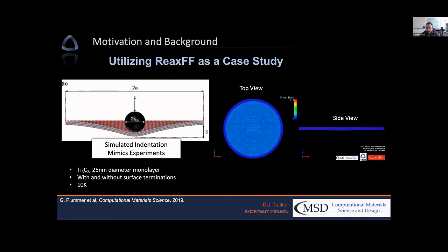We simulated the nanoindentation process as shown here on the right, up until the point of fracture. So you see this top view and a side view of the simulation continuing, where we color the atoms according to their shear strain relative to the initial undeformed state. And you can start to see that we get very complex deformation before fracture and then during fracture as well, or during the breakage of the monolayer. And because it's atomistic modeling, we have all this information from the atoms, so we can explore that behavior from a much more detailed point of view. As long as we believe that the potential is giving us reliable information there.